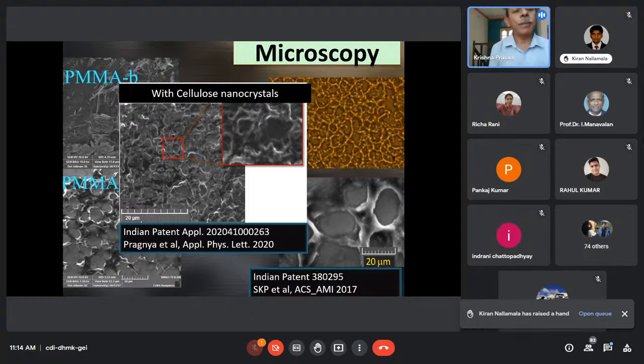As an extension of this, PMMA is not something which people are happy about in terms of its biodegradability. And so Pragna, the student, was working on how to bring biocompatibility to the system. Along with another postdoctoral person, Dr. Srividya, Pragna and Srividya worked together to come up with cellulose nanocrystals, which are now replacing the CNT to reinforce these systems. These cellulose nanocrystals were provided to us by a collaborator at IIT Roorkee. Professor Negi kindly provided these cellulose nanocrystals.